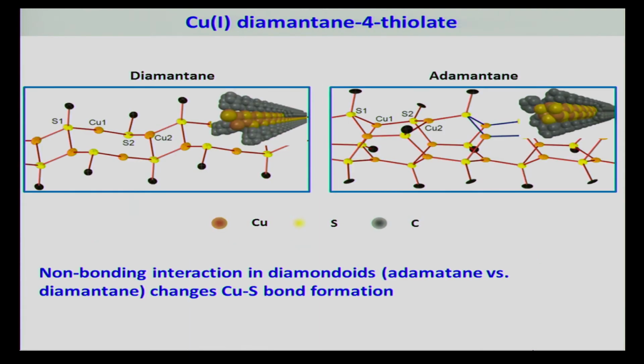So with the diamantane, you totally break the symmetry of the arrangement of copper and sulfur atoms as you have in adamantane. Instead of having a triangular stacking of copper and sulfur atoms as in the adamantane, here what you have is a square linked together with a rectangle sharing one edge, forming, instead of a molecular wire kind of structure, more like a twisted ribbon kind of structure. And again, this is surrounded by the diamantane species around it.